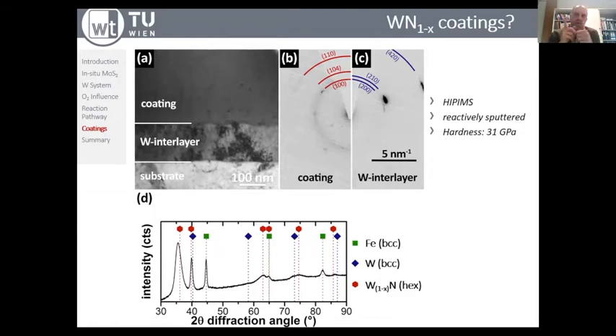Why? There are two reasons. The first reason is that tungsten nitride has a much higher surface oxidation rate, which helps regarding what I explained before, to have this intermediate pre-oxidized state, so that it can actually happen that you form tungsten disulfide. And the second point is that, of course, the tungsten nitride is much harder than the pure tungsten surface. So we produced tungsten nitride coatings by HiPIMS here. We had a hardness in our experiments of 31 gigapascal. As I said, it was reactively sputtered. And we also cross-checked then that we actually ended up with the right composition.